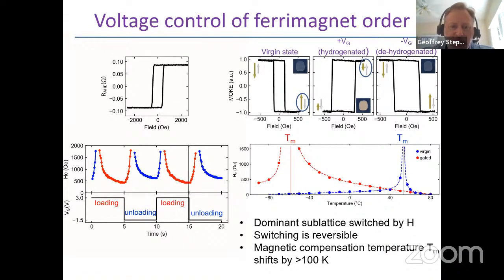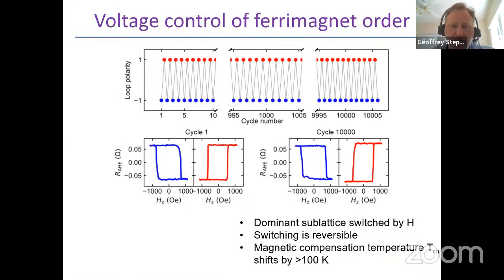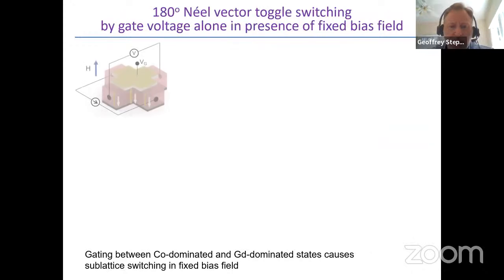And since we're changing the dominant sublattice, then that would allow either a field or in fact a spin orbit torque to have a different action on the magnetic configuration of the system in one of these states versus the other. So we've done a number of interesting things with these, but we've also found, you know, ionic devices are typically not well thought of in terms of speed and reproducibility, but we can cycle these kinds of materials for tens of thousands of cycles without any irreversible effects to the material. And we can drive switching quite fast.